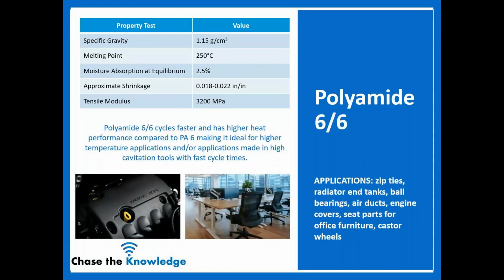Then we have our 6.6, which, as we also mentioned, has faster cycling and higher heat compared to 6, making it ideal for applications that need high heat and/or high cavitation tools that need the faster cycling time. So tensile modulus is about the same, 3200-ish. Again, quite a bit better and less flexible than the 1400 that you have with the PA12, and higher heat. Now our melting point of 6.6 is up to 250, where the 6 was only about 218. So as we mentioned, higher heat material than 6.